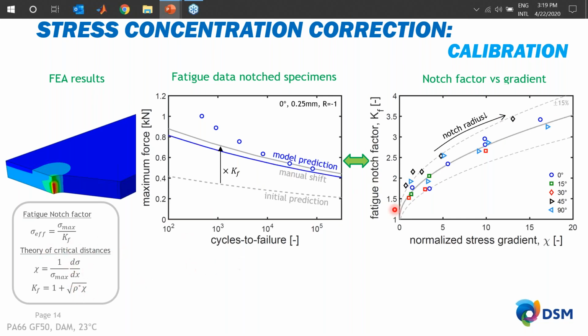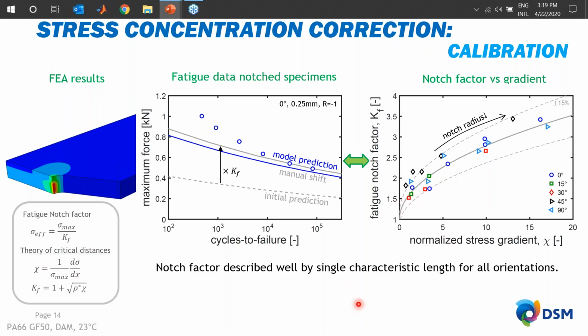So we just calibrate a certain characteristic length. And as you can see over here, with a constant single characteristic length for all orientations, we seem to describe this trend reasonably well over this entire range of normalized stress gradients. So we decided, okay, it's practical to just stick to a single characteristic length. And with that, we can also achieve reasonable model predictions. So the blue curve is the one corrected using Kf, and then the markers are, again, the experiments.